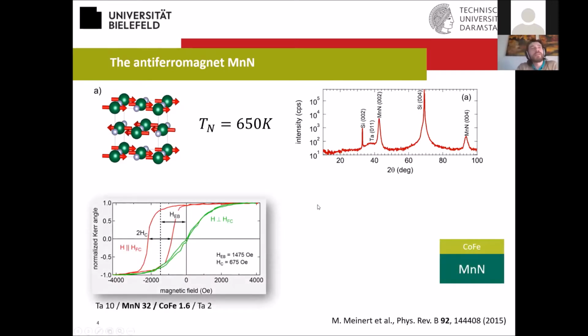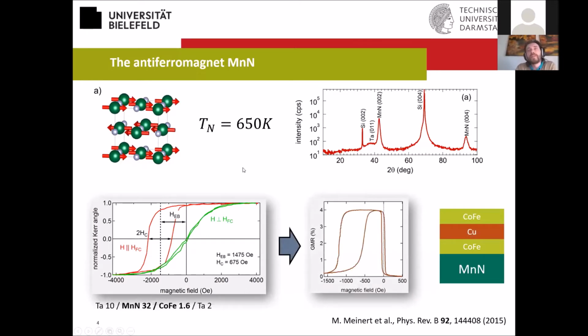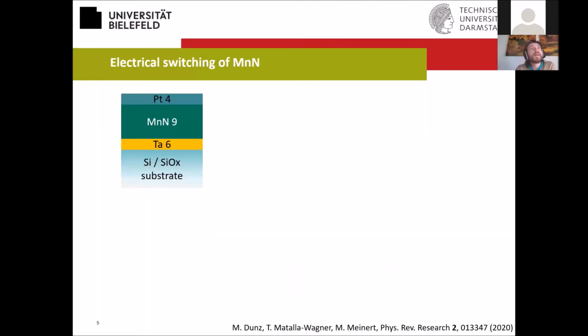Originally, we have done experiments on exchange bias with this material, and it turned out that we are able to get pretty large exchange bias fields, like 150 millitesla, with manganese nitride and cobalt iron as the ferromagnet. And also, we've done some proof of principle experiments to show the operation of a GMR spin valve with this antiferromagnet. So now we were interested in whether it's possible to electrically switch this material. So this is basically what we did.